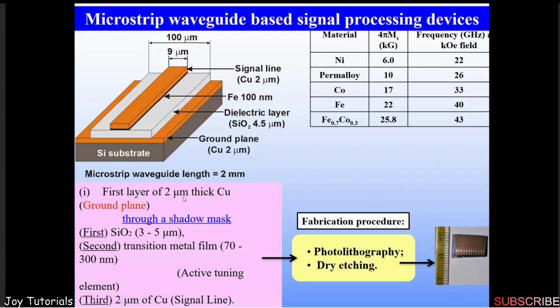What we do is first we deposit this layer, then through a shadow mask, we deposit the top layer to have a planar structure. In the second deposition, we do the layering of the dielectric, then the magnetic layer, and the top signal lines. Then by photolithography and dry etching, we get the device in this form. This has many devices inside. So what we can see here is not just a band pass or band stop filter. There are many elements which are phase shifters, many elements which are isolators. So one can have many kinds of devices inside a small chip, and then one can do the packaging of these devices to make the final product.